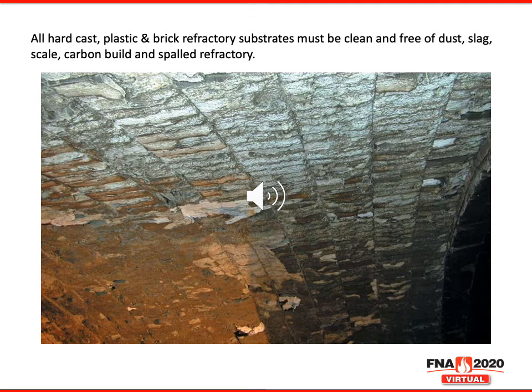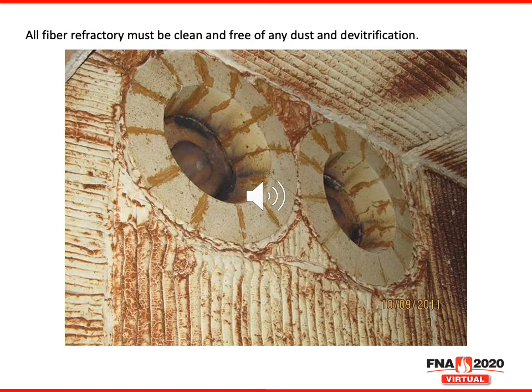As for any refractory substrate, all hard cast refractories, rammed plastic, and brick must be clean and free of dust, slag, scale, any carbon buildup, or spalled refractory. If the refractory is in need of repair, it is recommended that it be replaced and dried out per the manufacturer's dry out schedule before any coating installation takes place. All ceramic fiber refractory must also be clean and free of any dust and devitrification. Devitrified fiber is the brown, crusty layer that develops on the surface of ceramic fiber due to high temperature. This devitrified layer can be removed with the use of a currycomb, thus exposing the soft, friable refractory underneath.